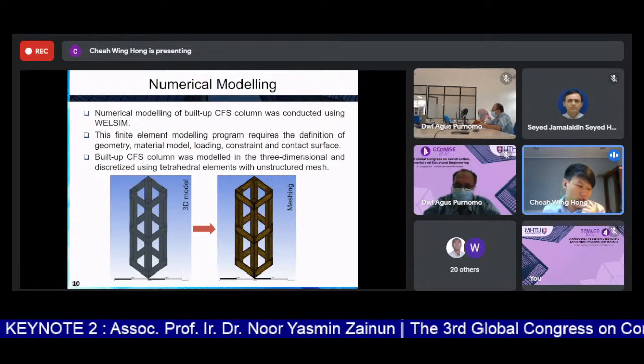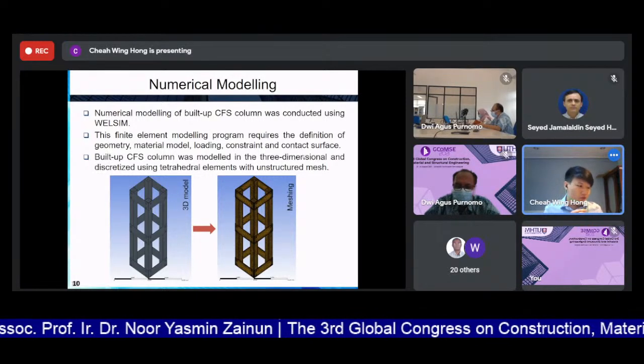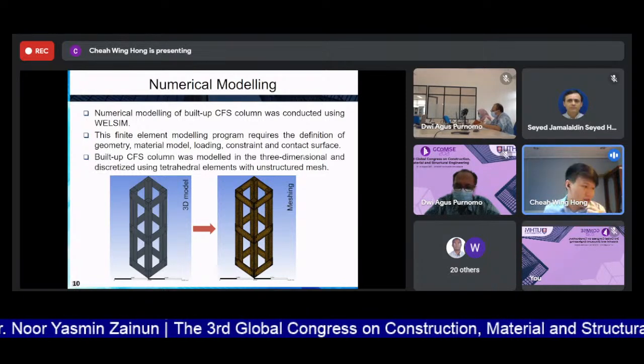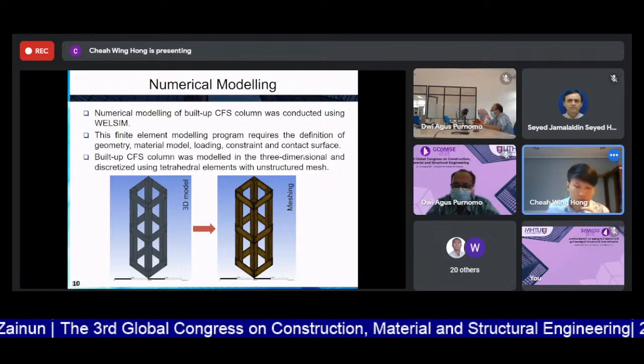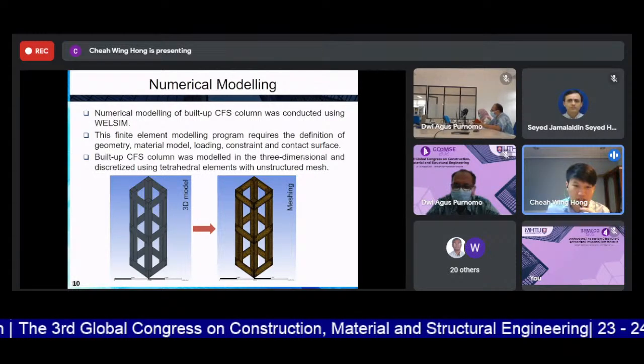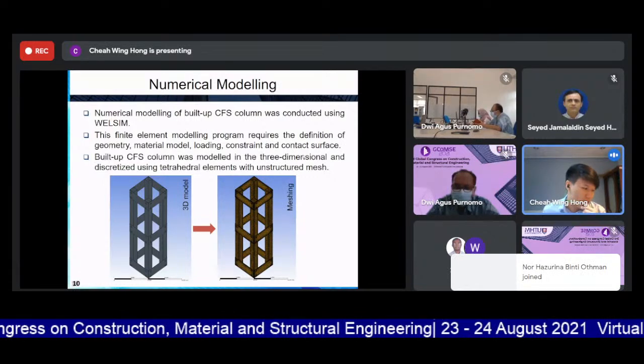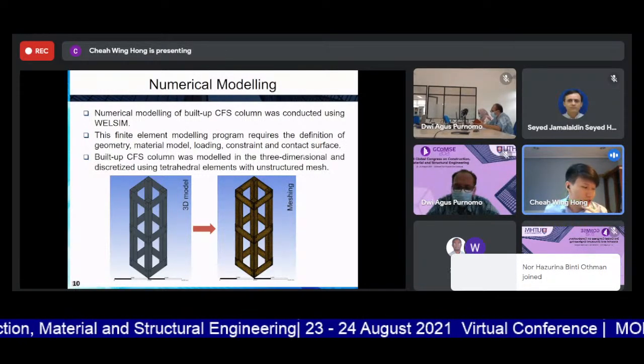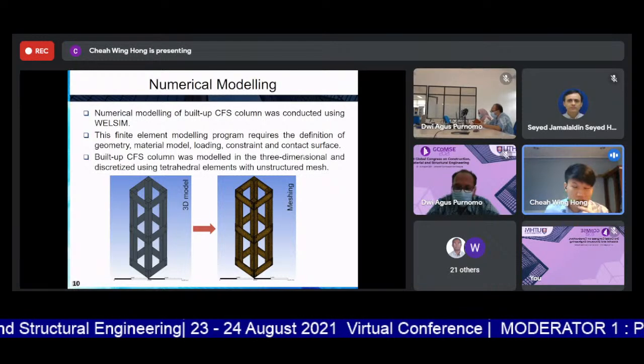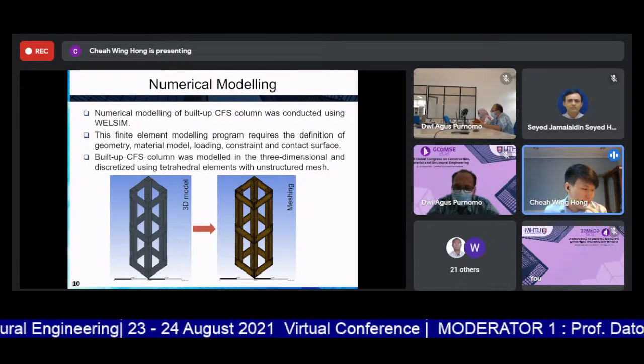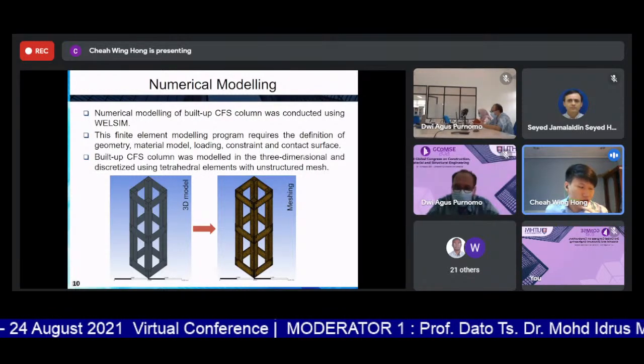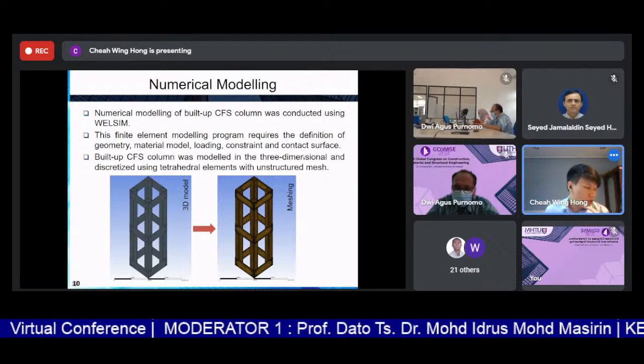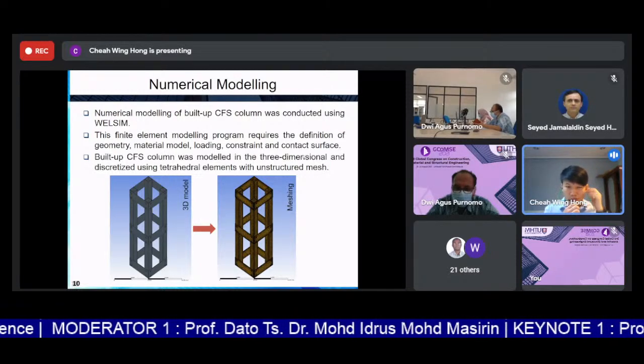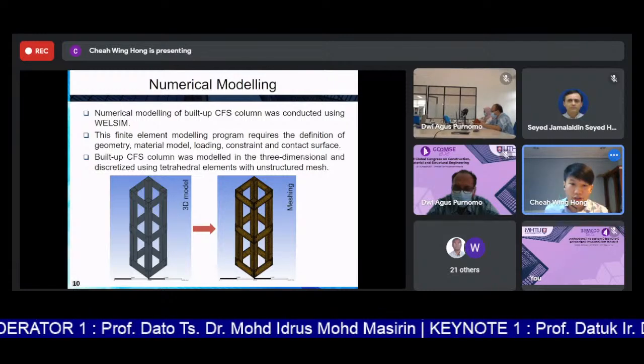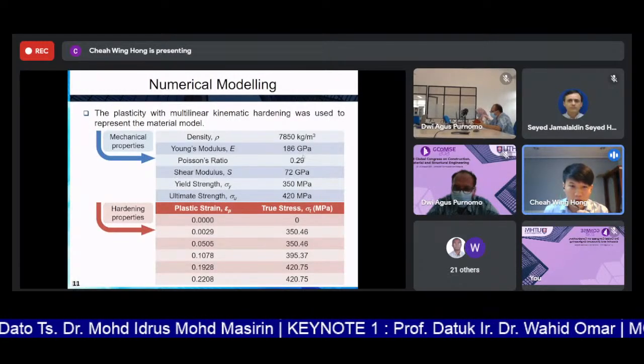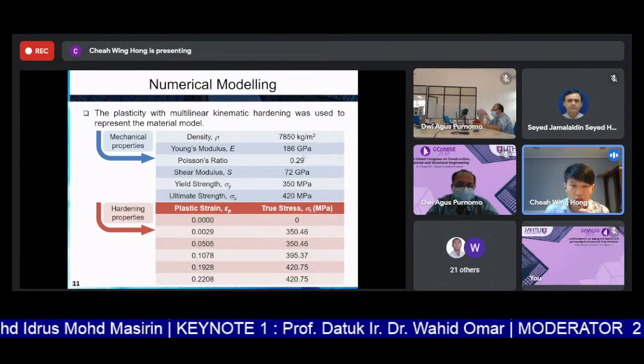I would like to draw attention that for the mesh size, we did not use a mesh sensitivity test. This is because, for WelSim, the mesh size is automatically defined using the adaptive refinement method. The size of the mesh is around 10 mm to 50 mm. This is why no mesh sensitivity analysis is required. Next we define the mechanical properties and the hardening properties of our model.